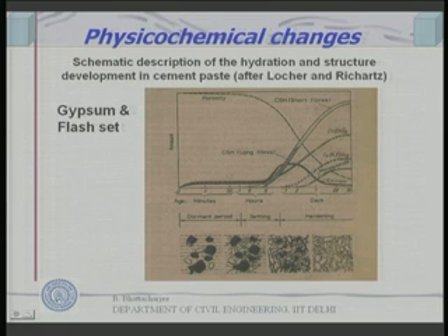The cement particles are here as if floated in water, and during the dormant period some reaction takes place and sort of fiber-like growth takes place. This is the phase where the setting is taking place, and these fibers grow, and the water-filled spaces outside the solid tend to become filled in with fiber-like materials, and this water reacts. So, the volume occupied by water now gets filled in by solids, and gradually more and more solids are formed, and in a very long run you will have a structure like this, which will have a large amount of solids with some pores which were originally occupied by water and some other special pores. We will come to this in detail.